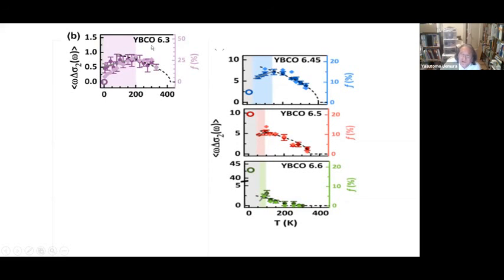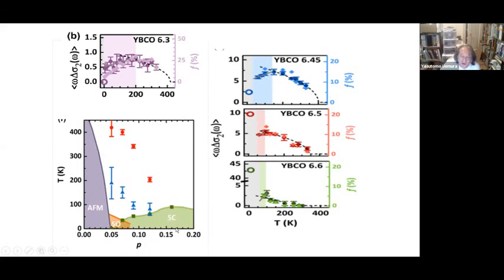But in, for example, 6.3, in equilibrium this material is not superconducting, but somehow light at least induces some of the carriers. So in this kind of case, light excitation could be not only killing the competitor, but also maybe inducing additional carriers. And it is somehow complicated in my opinion.